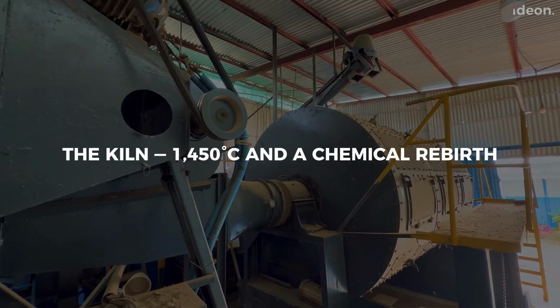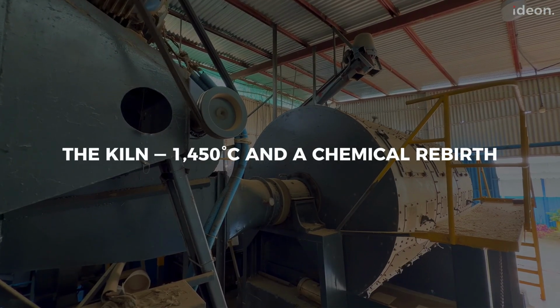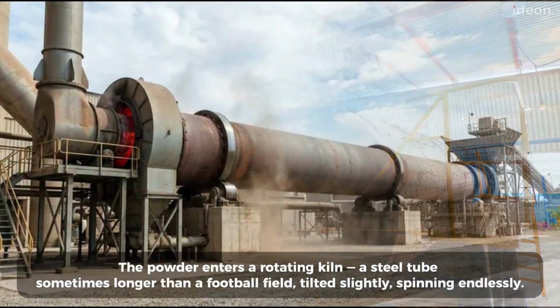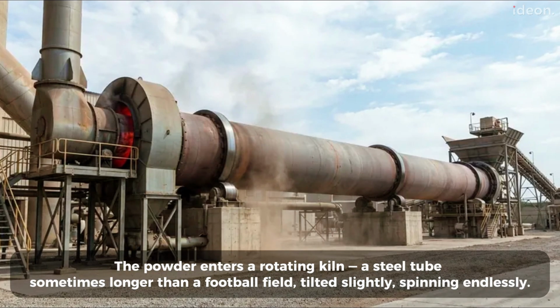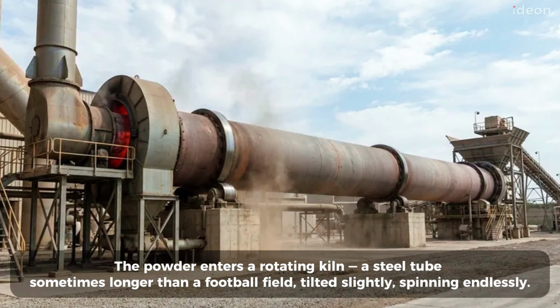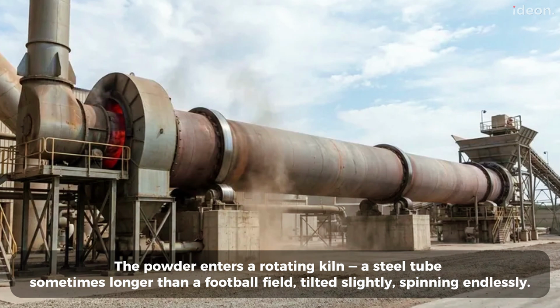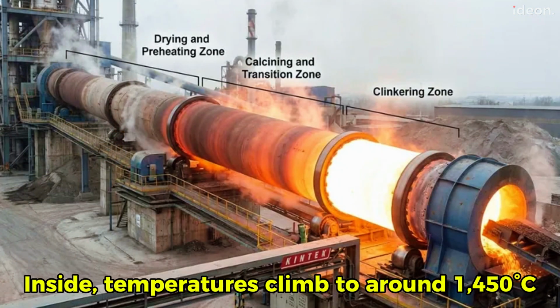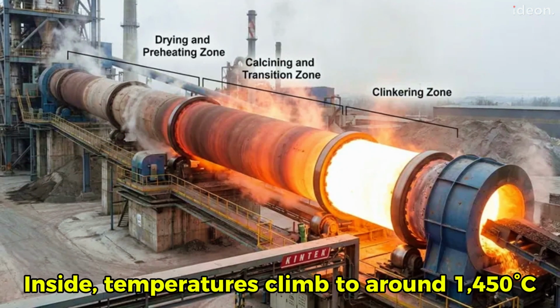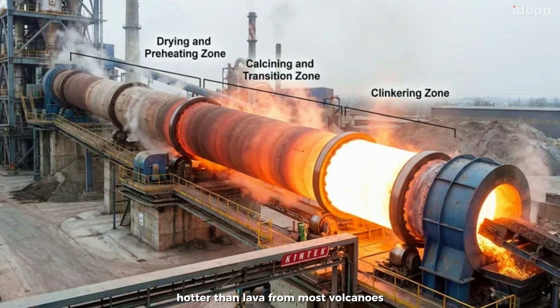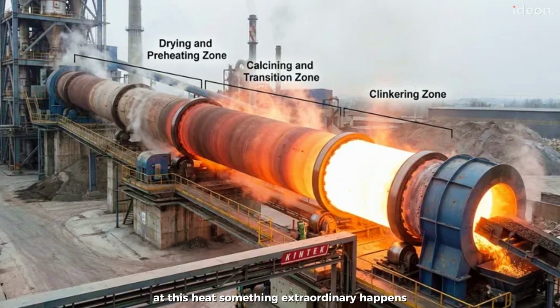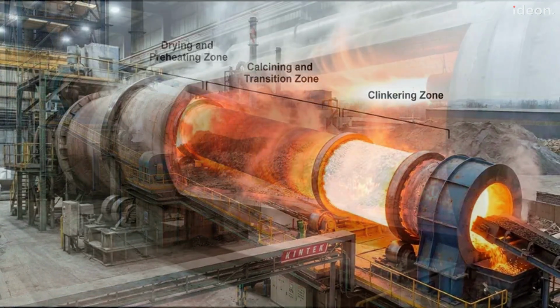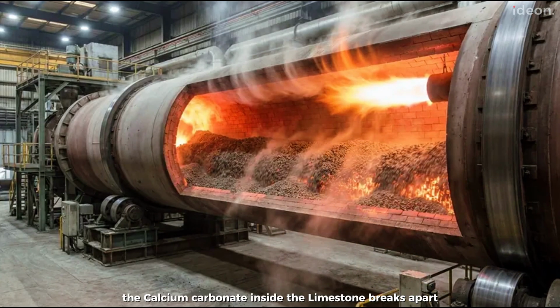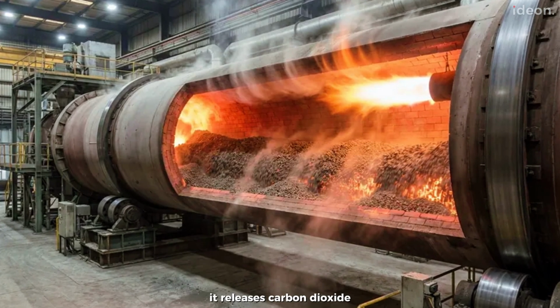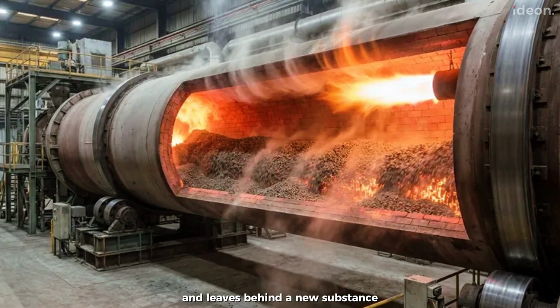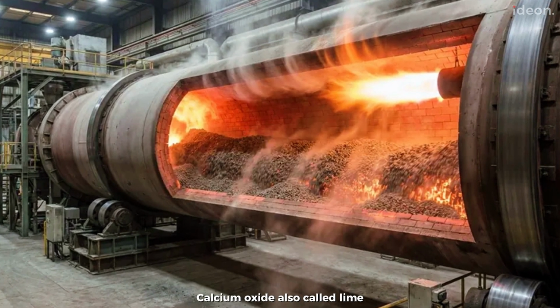Kiln, 1,450 degrees Celsius, and a chemical rebirth. The powder enters a rotating kiln, a steel tube sometimes longer than a football field, tilted slightly, spinning endlessly. Inside, temperatures climb to around 1,450 degrees Celsius, hotter than lava from most volcanoes. At this heat, something extraordinary happens. The calcium carbonate inside the limestone breaks apart. It releases carbon dioxide and leaves behind a new substance, calcium oxide, also called lime.